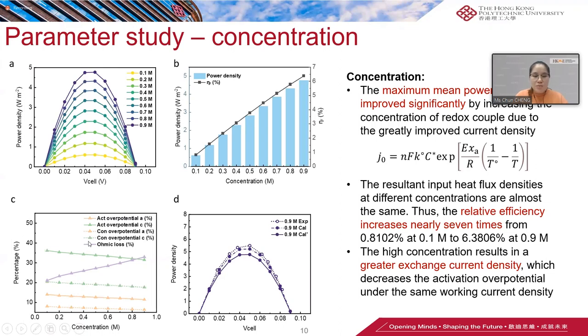The model and the parameters were tested with experimental data. Under the same working condition, the calculated power density matches the trend of the reported experimental value. So you could see that here the dashed line is the experimental value, and here is the data from our model. However, there is a little bit of a gap between the data from our model and the experimental data. This is because the effect of temperature on electrolyte conductivity is not considered in this model.